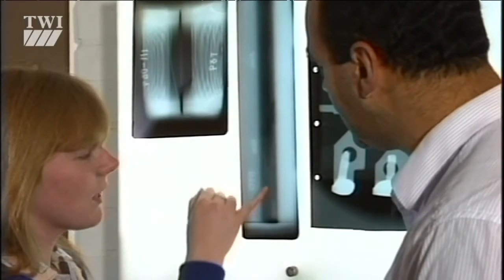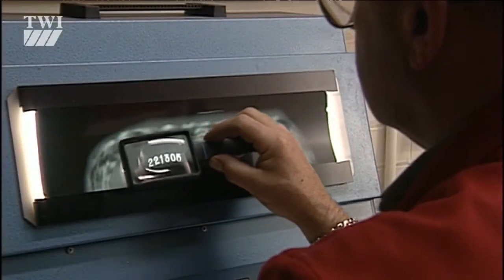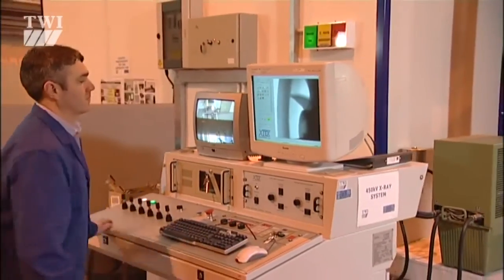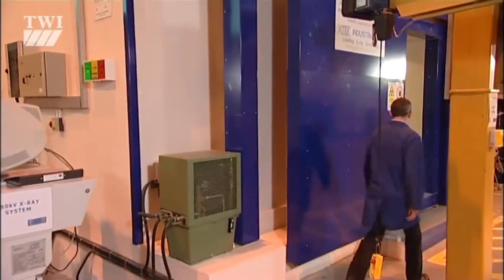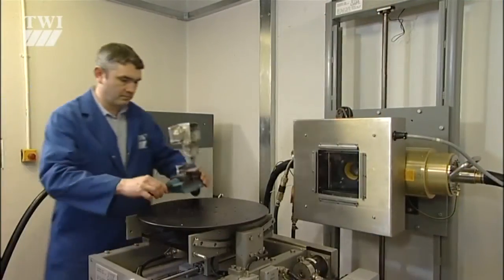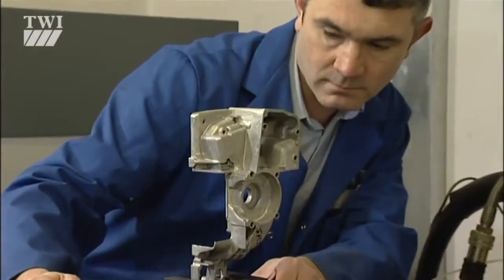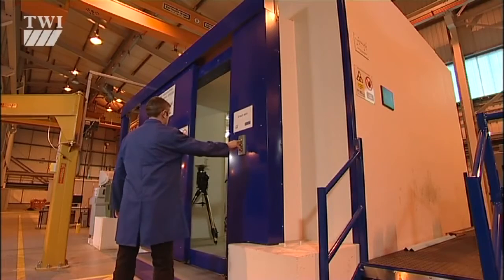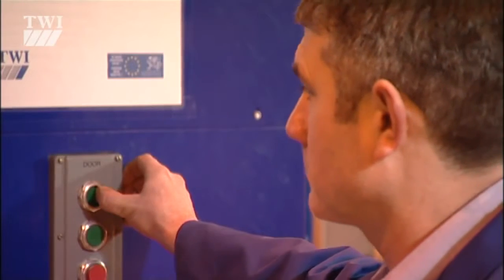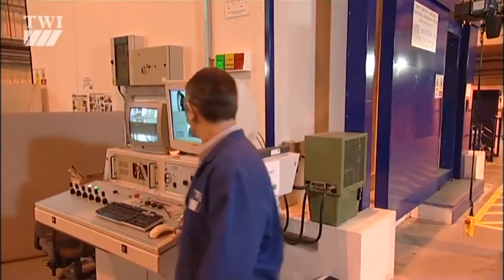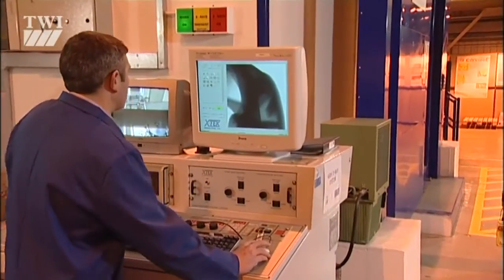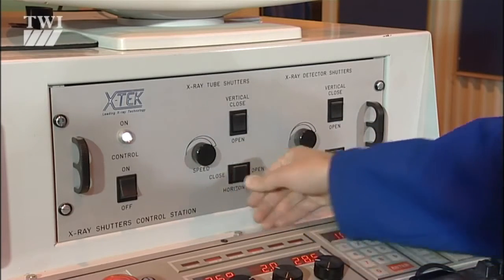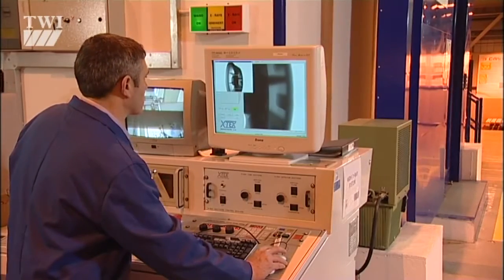In recent years, wet radiography — which uses photographic films and traditional darkroom technology — has been overtaken by digital radiography. Digital radiography relies on the ability of certain substances to fluoresce when exposed to x-radiation. The fluorescence emitted is made to create an analogue electronic signal, which can be converted to a digital signal by means of an analogue-to-digital converter. During testing, a fluorescent-coated surface is placed behind the test specimen; as the radiation passes through the specimen, it causes different levels of fluorescence depending on the dosage received, which is controlled by the specimen geometry. This is then converted to a digital signal and displayed on a screen.